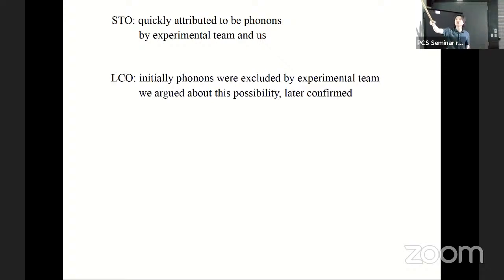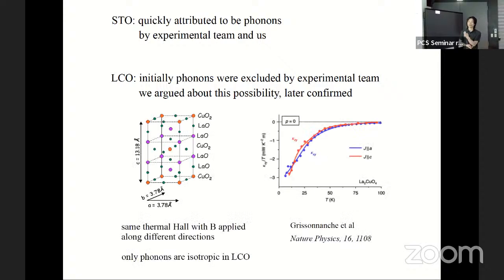And in the LCO, initially the phonons were excluded by the experimental team. But we argued about this possibility, and we communicated with the experimental team, and a later experiment confirmed that it comes from phonons. Let me emphasize this later experiment that confirms the phonon even in LCO. LCO, the cuprate material, is a layered material where each layer looks something like this in the C direction. So all the interesting cuprate physics happens as a quasi-2D system, which means the electronic degrees of freedom are quasi-2D. However, they measured thermal Hall transport in all three directions of the three-dimensional material, and they found all three directions look almost the same, which means the quasi-2D feature of the cuprate does not matter here. That means the only possibility should be the phonon, because only the phonon is the 3D thing in this material.